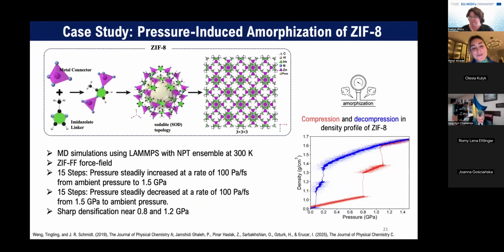Okay, so far we have also seen some examples based on the membrane concept. As a third case study, I also want to show you that you can study amorphous MOF structures. Anthony Cheetham and Tom Bennett showed that in our community, MOFs can also be glassy, or we can have amorphous MOF structures, and they started to show this using ZIF-8. You can either apply pressure using ball milling processes, for example, or you can heat your material, so you can observe the melting of your structure. Here, I want to focus on pressure-induced amorphization.